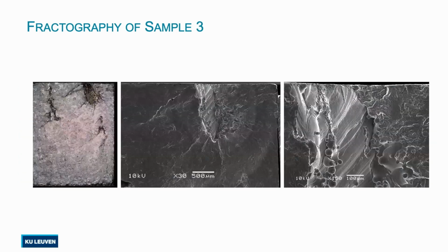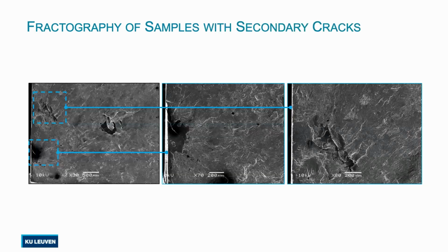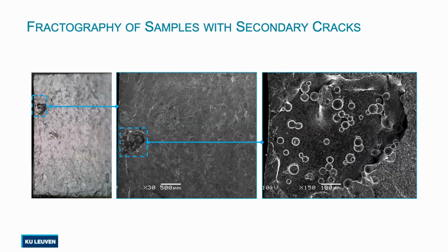For the other one, we found a big lack of fusion close to the surface, which actually caused the crack to start in the neck area because the stress was higher at that point. We have also found some secondary cracks, where there was a fretting fatigue crack, but also cracks starting at the neck area. So here you see another example of subsurface defect.